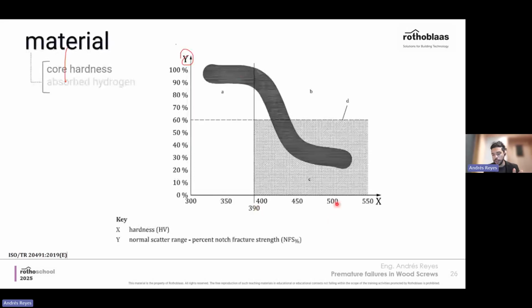Again, we can have a 500 Vickers fastener, and without the presence of hydrogen, it will not fail because of hydrogen embrittlement. Of course, you need hydrogen for hydrogen embrittlement. Nonetheless, if there is hydrogen, the higher the hardness, the more susceptible it is to failure from hydrogen embrittlement. And that doesn't mean either that you cannot have a hydrogen embrittlement failure mechanism with screws that are below 390. This just means that the risk becomes closer to zero. Let's say it becomes less.